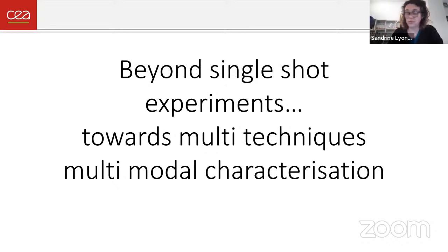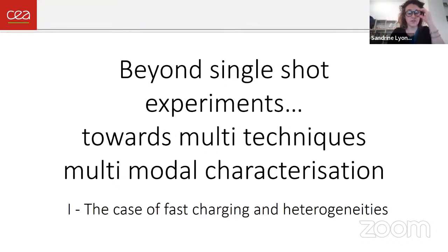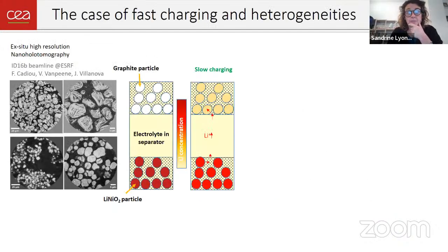And that is what I want to show you now on a first example, which is the case of fast charging and heterogeneities. This is something we're developing in the frame of the Big Map project. We're working on cells made of standard lithium-ion batteries with graphite at the anode. You see here nice images taken on ID16B at ESRF, the graphite particles, and the cathode is in lithium nickel oxide, LNO material. So the question we have is, when you charge your battery quite slowly, what happens is you will have the lithium ions moving from the LNO to the graphite, and this will be homogeneous.